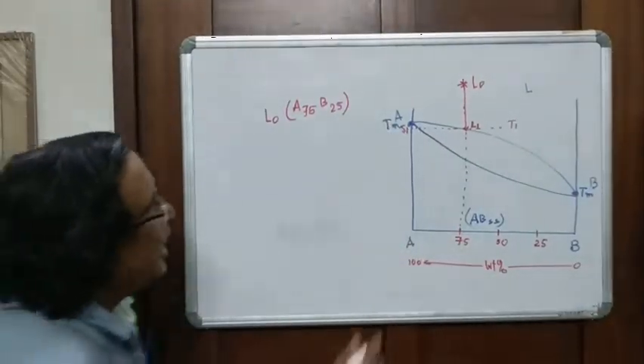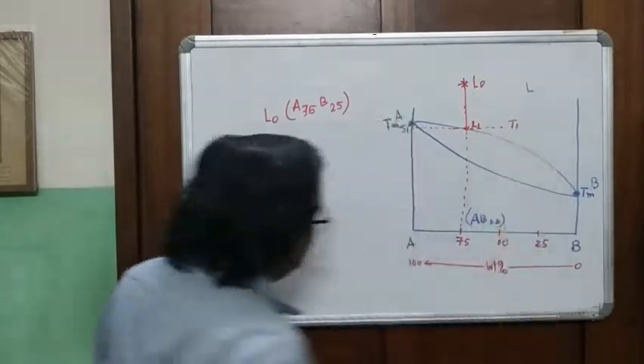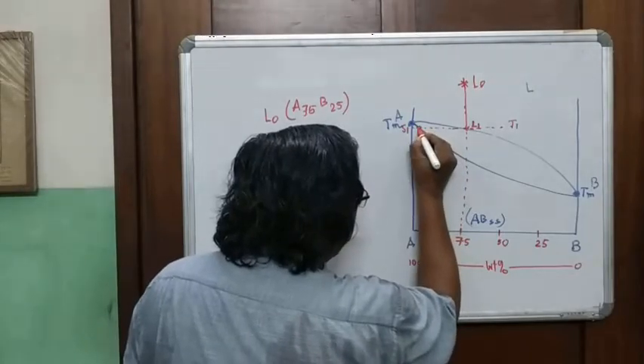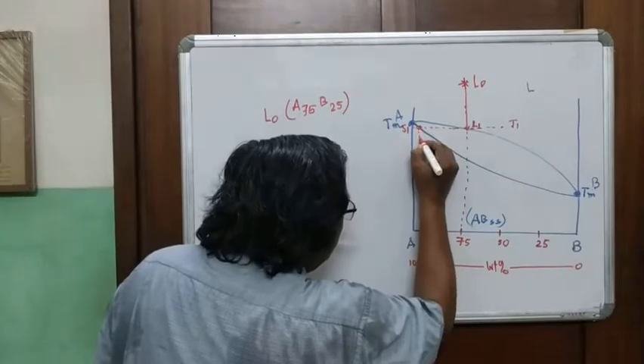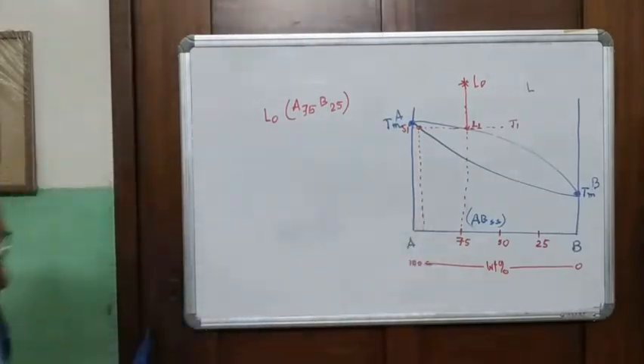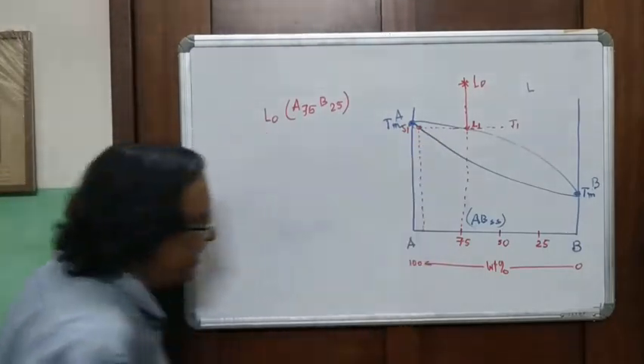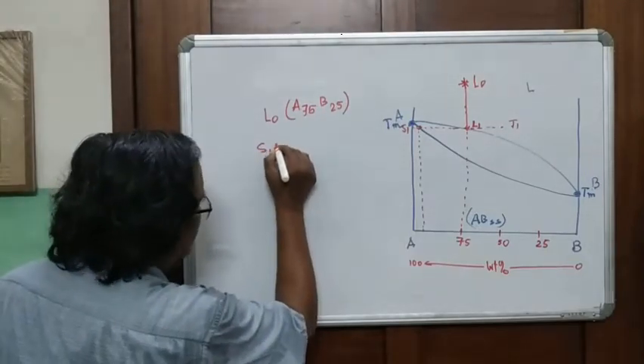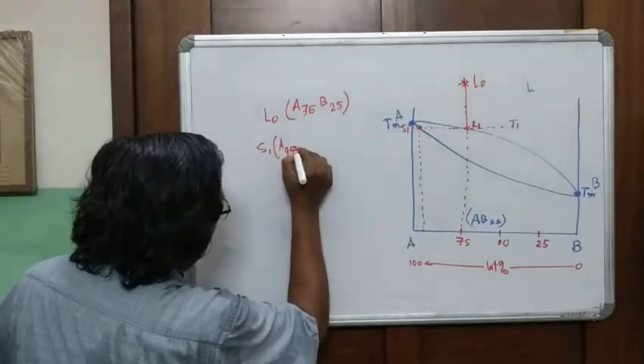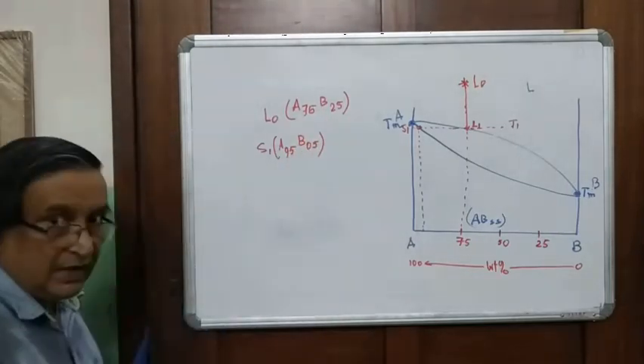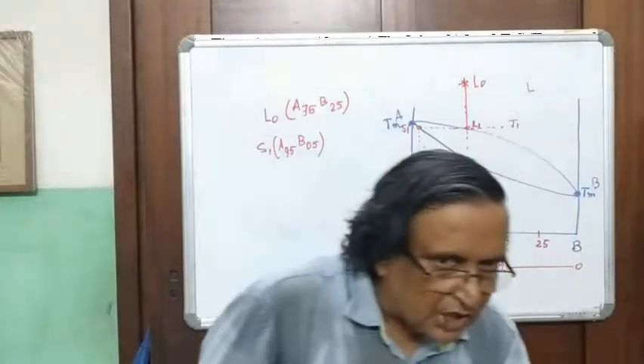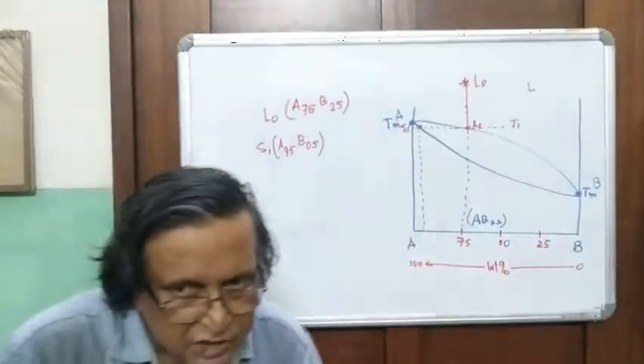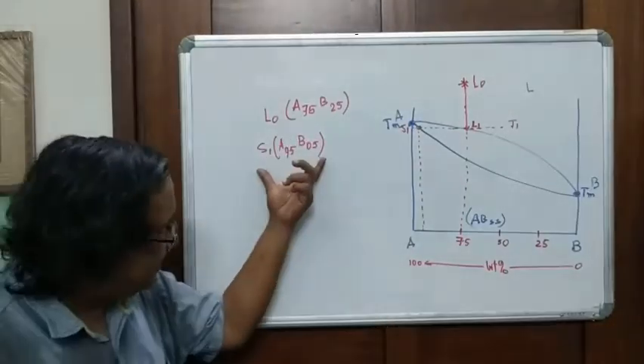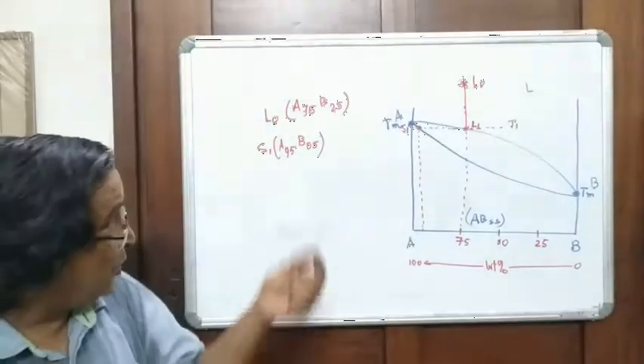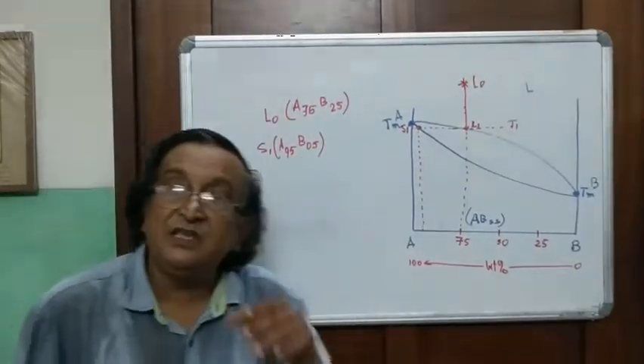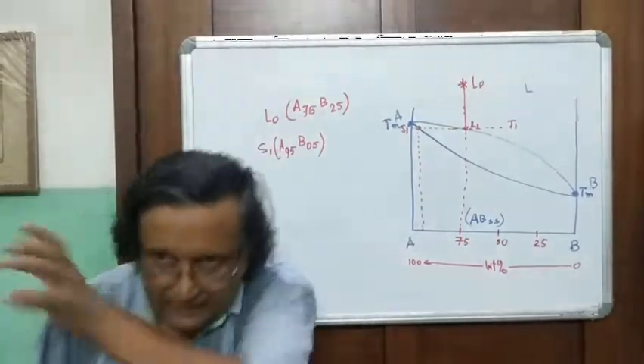And how do I find out? I take a line at this temperature, say this is T1, at this temperature I draw a line, and this point here is the composition of the first solid. So corresponding to L1, you produce a solid which is S1, and that S1 then has the composition of A95 possibly and B05. Now remember, this is not a mixture of A95 and B5. No, it's not a mixture of pure A and pure B. Here you have a mineral AB in which the component A is 95% and the component B is 5%. This makes up the mineral AB, solid solution.